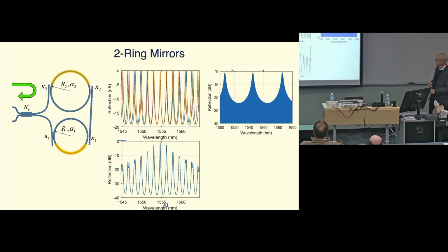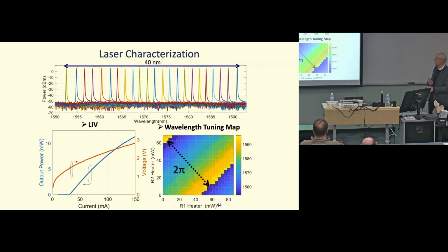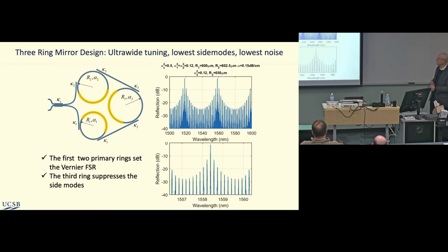So if you look at the composite mirror, it looks like this. Again, you need to suppress this enough that these lines don't lase, so there's a lot of design that goes into it. But here's an example: this laser tunes across 40 nanometers, has reasonable thresholds and powers, and a very clean tuning map. Whether you tune one ring or the other ring, you can tune across the full 40 nanometers. It's very predictable, very reproducible, and that's what you need for real products.